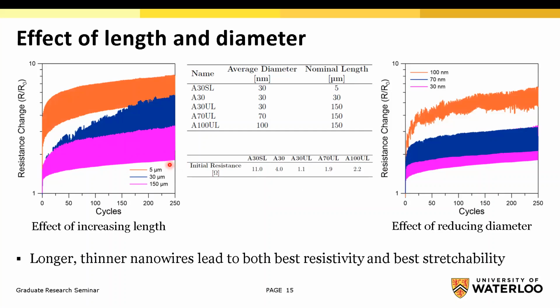magenta plot is showing the 150 micron. This plot is showing the resistance change for the stretching cycles, 250 cycles, and you can see for stretchable electronics, minimum resistance change is better. So a minimum resistance change is expected for stretchable electronics. We can see that here we have the minimum resistance change with the longest nanowires, 150 micron, and you can see the longest nanowire has the lowest initial resistance as well.